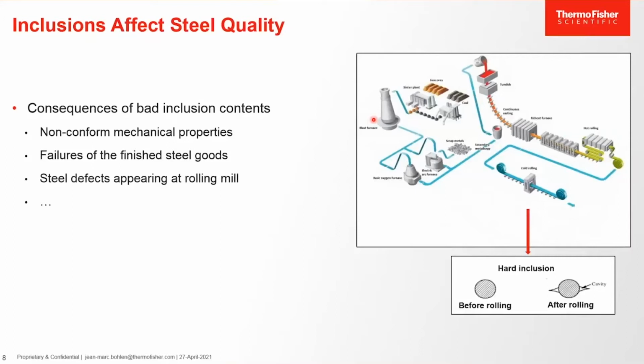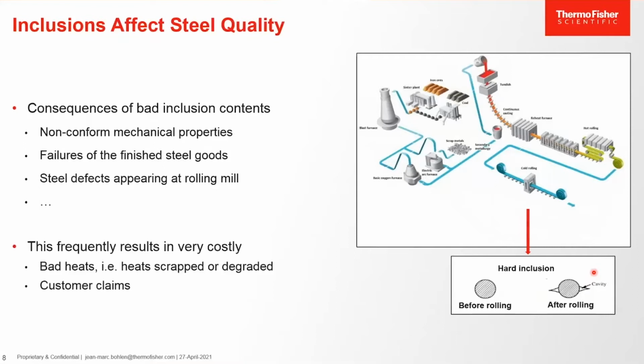What happens when a hard inclusion goes through the rolling mill? As you can see on the lower right picture, there is creation of some defect of the matrix due to the fact that the inclusion is not broken. And this kind of defect is happening in the direction of the rolling direction. So these kinds of things frequently result in very costly bad heats. In other words, heats that are scrapped or degraded or customer claims.